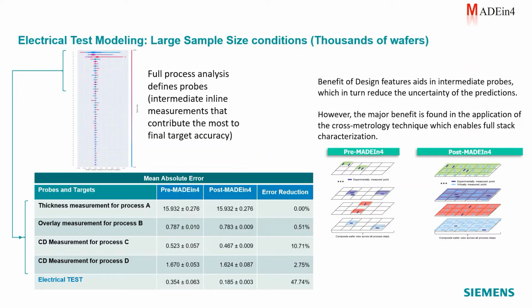Now, what happens if we have a large sample size? When we have thousands of wafers, we are going to perform a very similar analysis in which we want to take a look at, after the full process sequence, what are all of these different targets or probes that need to be extracted that are able to identify the benefit in the electrical test. In a similar fashion to the previous example for back-end of line, this is the mean absolute error. If we use a technique that is pre-MADEin4, in which we are subject to the fact that there is data missing, we can see that there is a certain amount of error.